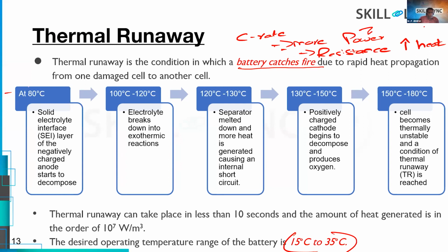Now, at 80 degrees Celsius, what happens in batteries? When the battery attains 80 degrees Celsius, the solid electrolyte interface layer of the negatively charged anode starts to decompose. A battery consists of both anode and cathode, right? But the interface layer of the anode starts to decompose at 80 degrees Celsius. This is the starting point of thermal runaway.